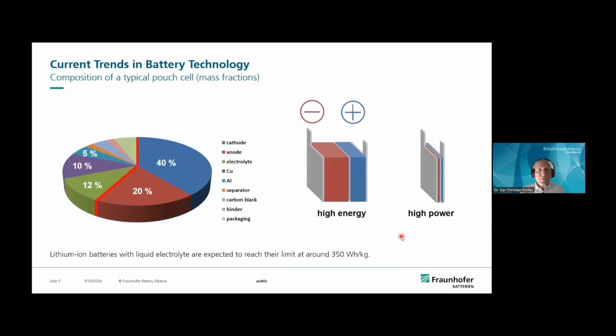The composition of a typical cell you can see here. This blue amount is the 40% cathode active material. The anode contributes with 20% active material. In these two components, you find the energy density, the energy storage is in anode and cathode. And all the other components you need, but they dilute somehow the energy density. So you need electrolyte, you need the current collectors, copper and aluminum foil, and also the binder and carbon black as conductive additive and the packaging and so on.